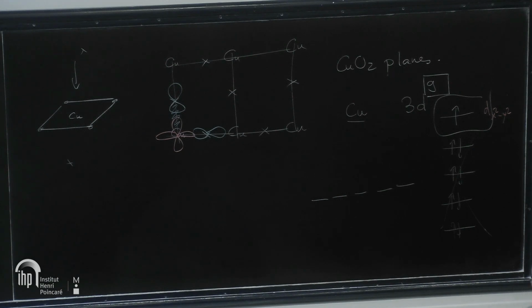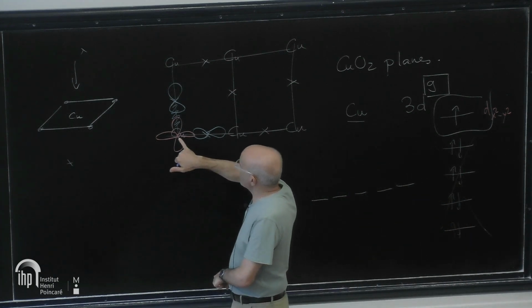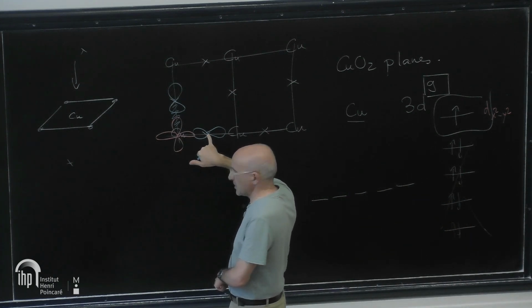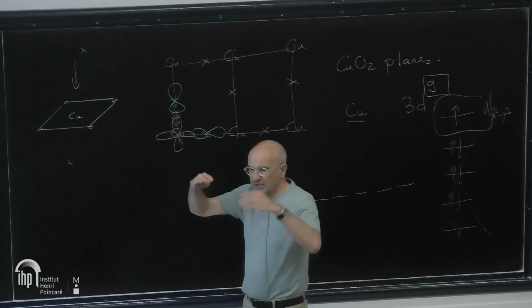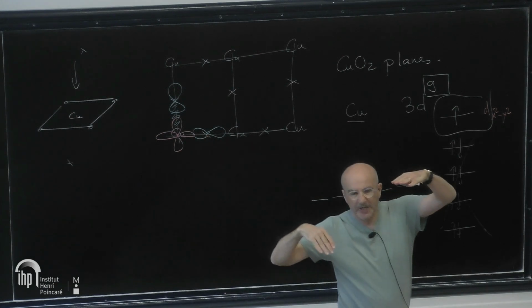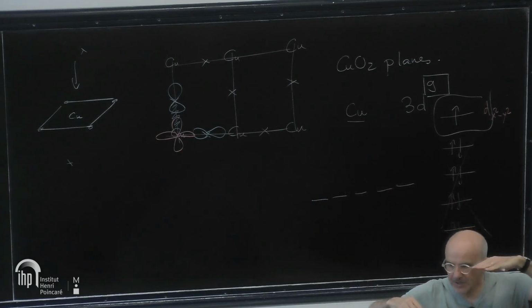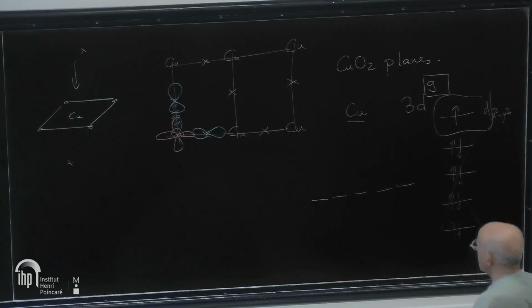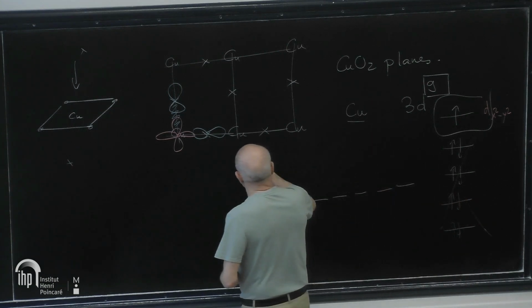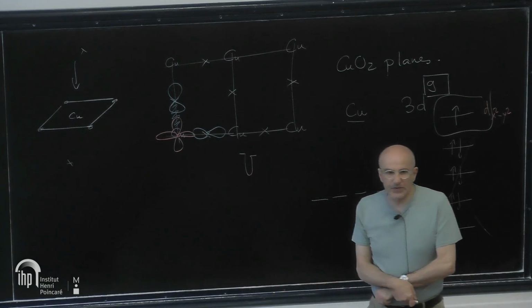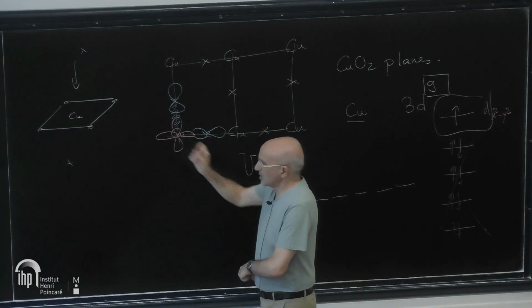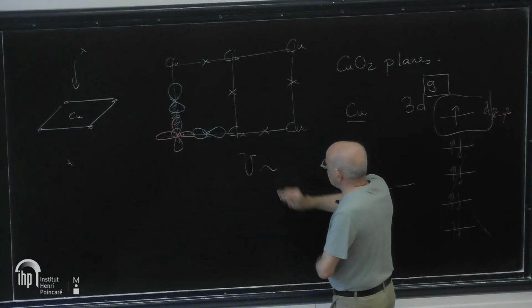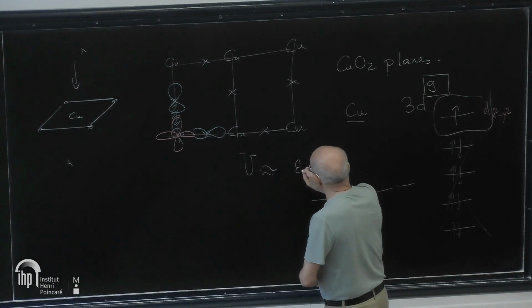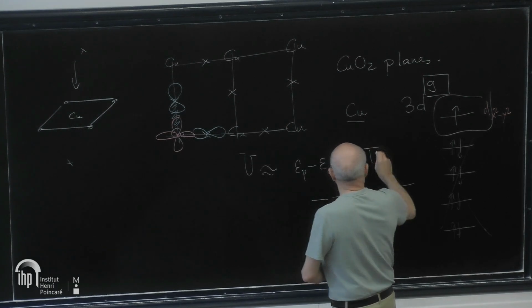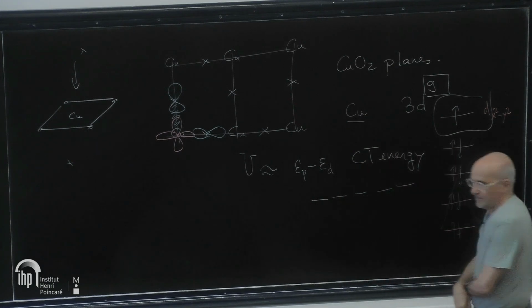And an on-site interaction, which is actually due to the fact that if you need to hop from here to here, you have to pay a price, which is the nominal energy difference between the atomic level position of the d state and of the p state of oxygen. So U, in this context, if you really want to reduce this to a single band model, is not the on-site Coulomb interaction on copper, but it is much more related to the energy difference, the so-called charge transfer energy, between copper and oxygen.